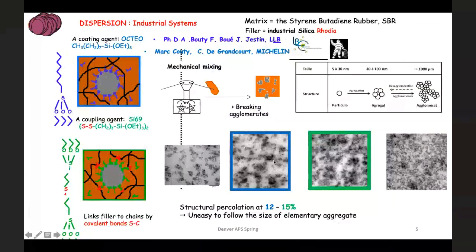And it would also be interesting to see how filler volume fraction could affect that. So for example, if you have more filler, the segment length that would connect the different nanoparticles together could be smaller. I think that could potentially be a very rich study as to see the effects of those layers at those small deformations.